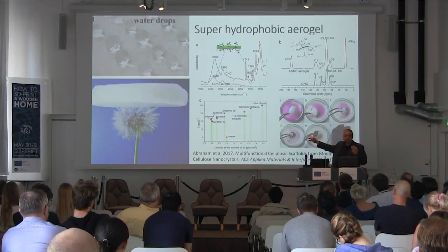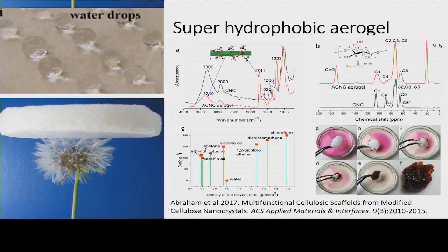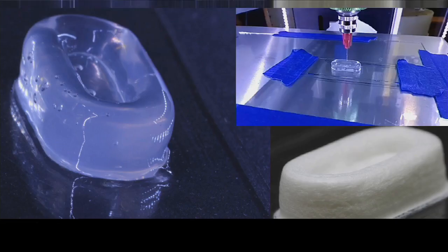Well, sometimes we would like nanocellulose to be hydrophobic. Because nanocellulose, of course, contains a lot of hydroxyl groups that can be easily modified, we have shown that by simple acetylation with green chemistry, we've been able to make superhydrophobic foams and superhydrophobic nanocellulose materials that, again, can be useful for many things. Here, in this case, you see an almost aerogel that has an extreme capacity to absorb organic materials. Here, we've shown that we can absorb about 200 grams of chloroform in only 1 gram of foam. So that can be used for oil spills and lots of other interesting applications.